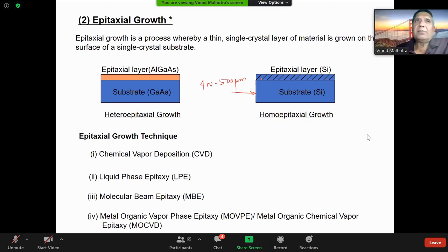If this is made by the Czochralski method, then we have to deposit another layer of single crystalline silicon on top of it. So the crystalline structure of atoms here acts as a template. And when you deposit silicon on it, this is very high purity and high fidelity, because you use a different process and you make sure that this crystal is perfect or near perfect. The bottom crystal provides you a template to grow.